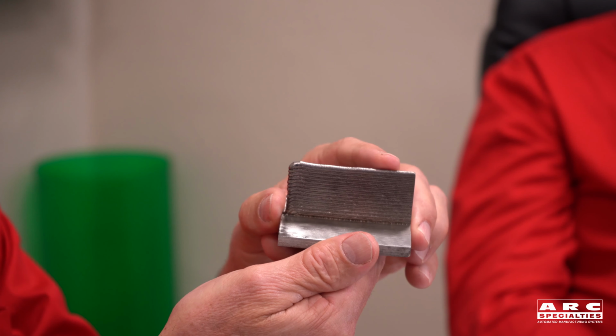So this seems to be a great technique if you want thin shapes. So what is this, about 3/16 thick? Yep. 3/16 wall? Okay. Are we doing any work on heavier sections? Yes, we've done some strip and some sub-arc in the past, and so those are much bigger, 30 millimeter wide strip. So you can really get anything in between 3/32 to inch wide, 2-inch wide.